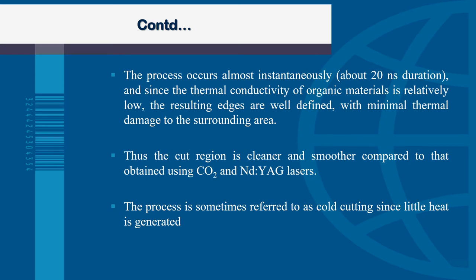So the process occurs almost instantaneously, about 20 nanoseconds in duration. And since the thermal conductivity of organic material is relatively low, the resulting edges are well defined with minimal thermal damage to the surrounding area. Thus, the cut region is cleaner and smoother compared to that obtained using CO2 and neodymium yttrium aluminium garnet lasers. The process is sometimes referred to as cold cutting, as I mentioned before, since little heat is generated.